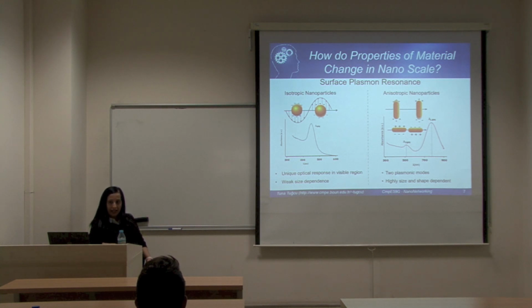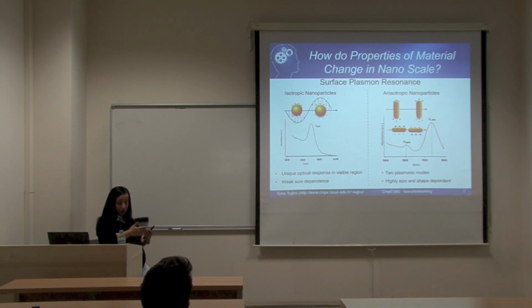And the thing is, this peak is quite sensitive to the aspect ratio of your nanoparticle. Meaning that when you change the length divided by the diameter, meaning the aspect ratio of your nanoparticle, you can play with this peak, and you can have a system which gives you a response in the near infrared region. You can go up to 1,300 nanometers, 2,000, 3,000, 4,000. You can increase this, or you can come back to the redshift, and you can have a response somewhere here. So you can design a material where you want a response. Okay, it's another property that we actually use when we are working with nanomachines.